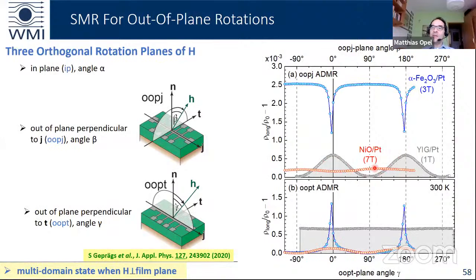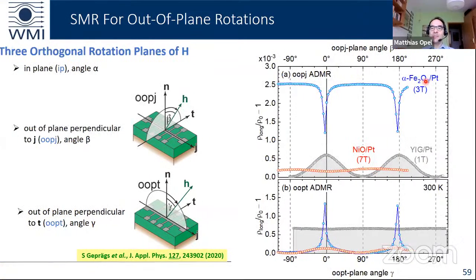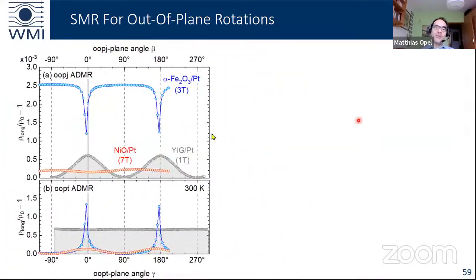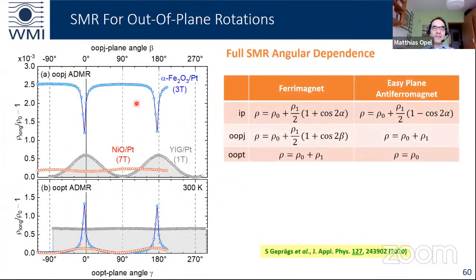In red you see the nickel oxide. In blue you see the magnetite, sorry, the hematite. And you see that for these out-of-plane rotations, the behavior is different from the YIG. It is summarized in this table. So for the out-of-plane rotations in easy-plane antiferromagnets, we expect constant values when we rotate the magnetic field out of plane perpendicular to J and perpendicular to T. We find a high resistive state for this rotation and a low resistive state for that.